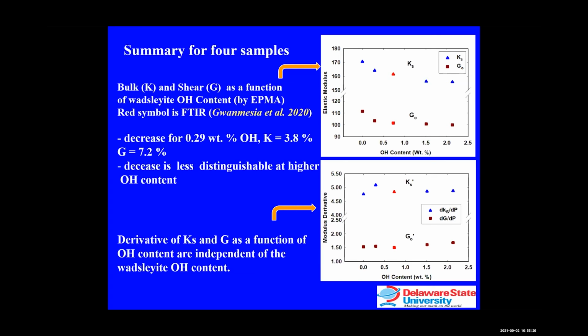And at the bottom right-hand corner, we have plotted the pressure derivative of the bulk modulus and the shear modulus as a function of the water content. And we see that both K prime and G prime are almost independent of water content. And this has already been shown by some studies by Brillouin scattering. So water does not affect K prime and G prime, but causes a drop in the bulk modulus and the shear modulus.